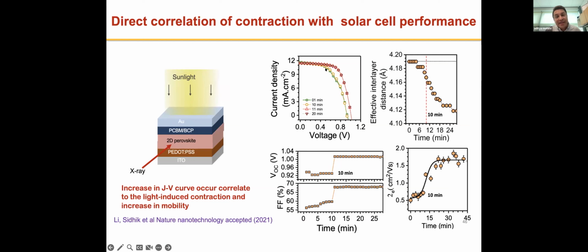And so on doing that, what you find is that just when you see a jump in your photovoltaic device, which is shown here in the voltage and the current, you also start to see this interlayer contraction. And so that's where you start to see this increase in your efficiencies. And we think that as you start to get this contraction, you hit a certain critical point where you start to induce a transport channel in the out of plane direction, which did not exist. And that's what leads to an enhancement both in your voltage by suppressing recombination and also inducing better charge collection, which is reflected in your fill factor.